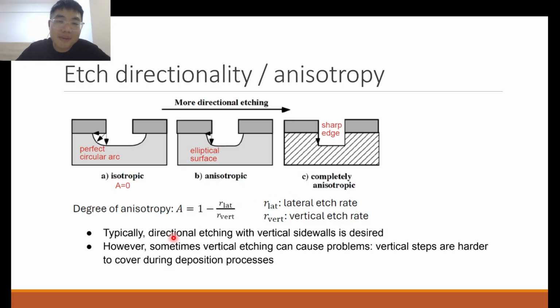So this diagram here shows it very clearly. If you have a completely directional etch, we have a sharp edge, you want to etch down only, so you etch it down. However, when you have an isotropic etch, it etches in all directions evenly, so you start to see a curvature, a curved surface, right? Why? Because it starts etching not just down but left and right, correct? So it forms a curved surface.